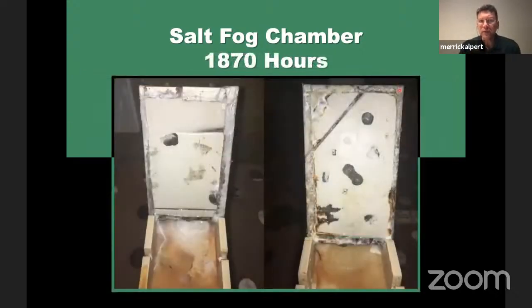Chevron then takes those 2 side panels and puts them into salt fog for months, 1,870 hours. Same result. Look at that. You see no corrosion. If that was paint, it would be blistered and bubbled and it would all be gone. There's no corrosion. The only corrosion you see is actually just the rust bleed from the uncoated back of the panel.